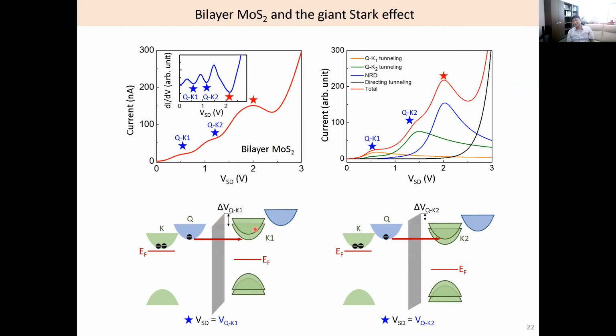Of course, this could be done by STM, but I haven't seen such a result, and this is a device scale result. I didn't mention, but if we study MoS2 by STM, it is weird. We see a wide range of band gaps, from 1 eV to 3 eV, 4 eV. It is still mysterious for me. It is not seen by photoluminescence or other optical spectroscopy, but local strain and other things are quite sensitive for 2D materials. But in my study, we did a device scale result.